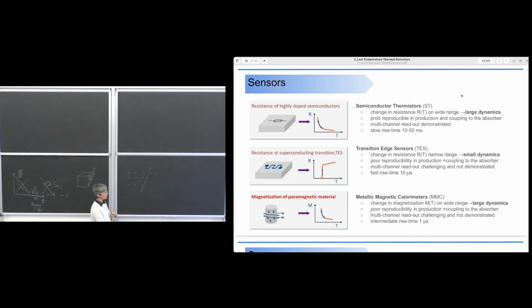The problem: these sensors have a very high sensitivity. They can produce very high signals, but the drawback is that they have a small dynamics, because when the rising temperature is too high, they are outside the transition, and they move to the normal state of the sensor. So they have small dynamics. They have a poor reproducibility.